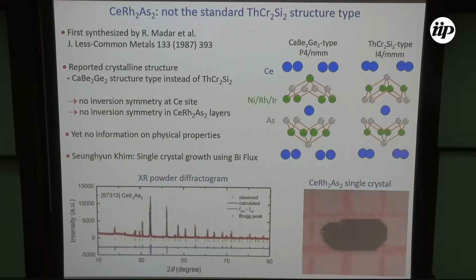So we looked at CeRh2As2 for other reasons at the beginning. One of the points of this compound is that it's not the standard ThCr2Si2 structure, which is, for example, in the iron pnictides or in CeCu2Si2. Instead, it is the CaBe2Ge2 structure, where in one of the two layers you exchange the arsenic and the rhodium position. You just interchange in an ordered way, and then you get from a body-centered to a primitive structure.